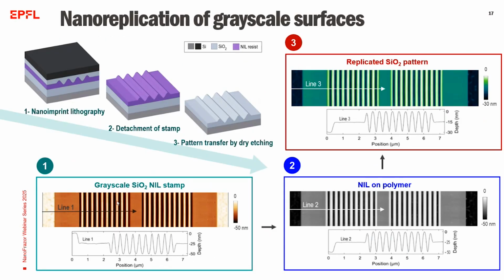And here, for example, you see an ultra-high resolution grayscale stamp fabricated using this method. And these sinusoidal nanopatterns were then replicated onto a polymer layer on a different substrate. And following this imprinting, a second dry etch transfer process was employed to transfer the pattern onto the final target substrate. And through this combined approach, we achieve large-scale replication of grayscale structures onto wafers.